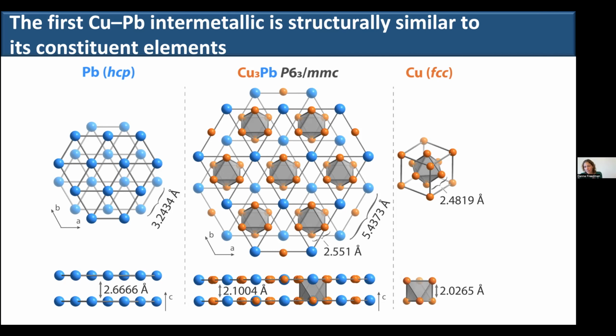We hypothesize, but have no evidence for this, that one reason that drives the structural formation is the comparable electronegativity of lead and copper in this space. But we have not come up with a good way to probe the grand question of what drives the formation of one particular solid state structure.